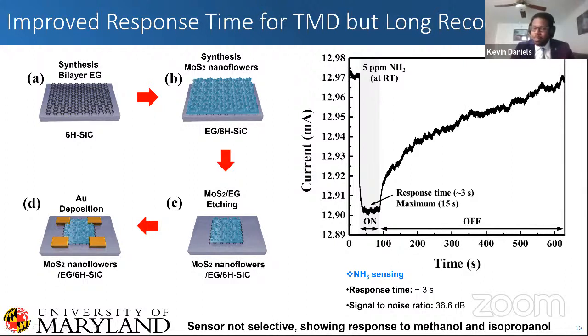The issue is this sensor is really not selective, and it shows response to methanol and isopropanol as well, so it's not selective at all, on top of having an extremely long recovery time here. And so the idea was, okay, would we be able to get a better result out of a material with the enhanced charge transfer that we typically see in transition metal dichalcogenides?